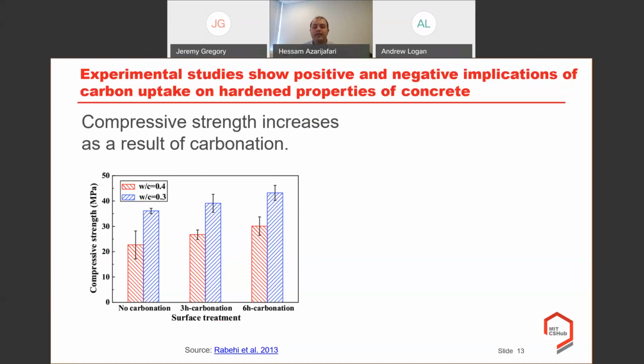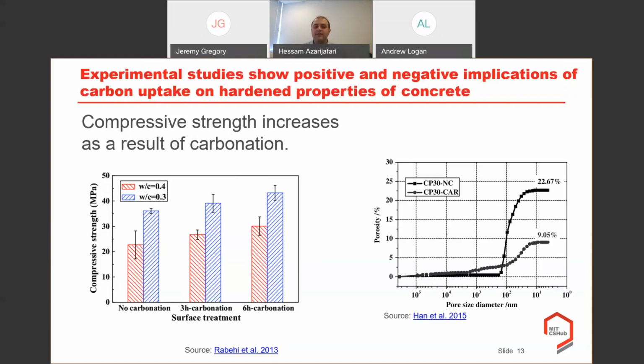On the other hand, we have calcium carbonate, one of the products of the carbonation, deposited in the small voids within the cement paste. So we have a denser binder in the concrete. Here, this microstructural analysis will show that better when you have a normal concrete or a carbonated concrete. This curve belongs to a normal concrete with compressive strength of 30 megapascal, and this one is a carbonated concrete.